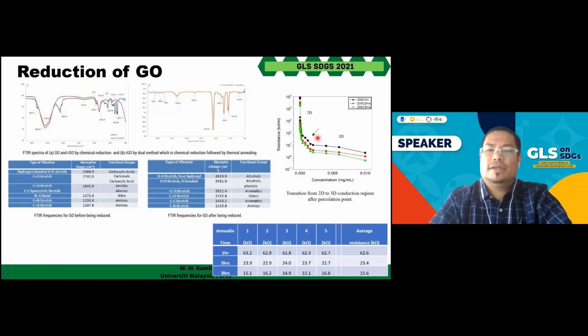So once we have completed the reduction process, we do the electrical measurement for the double reduction process. Basically we heat our sample first at 200 degrees C for 1 hour, and then we increase it to 3 hours at the same temperature, which is 200 degrees C. And then we fabricate a thin film of reduced graphene oxide on top of our silicon substrate.